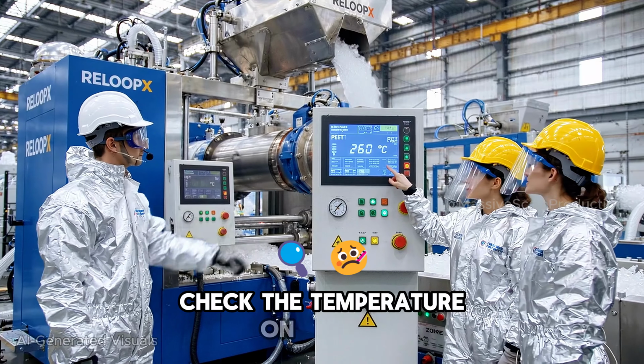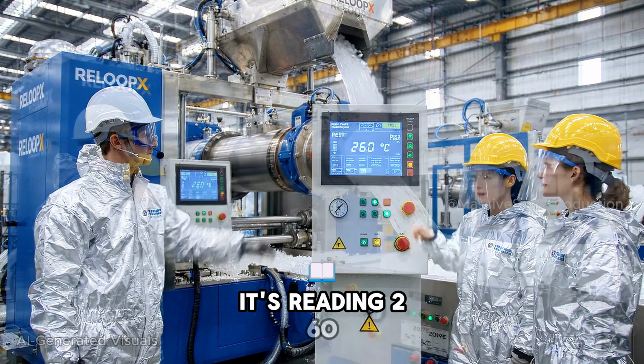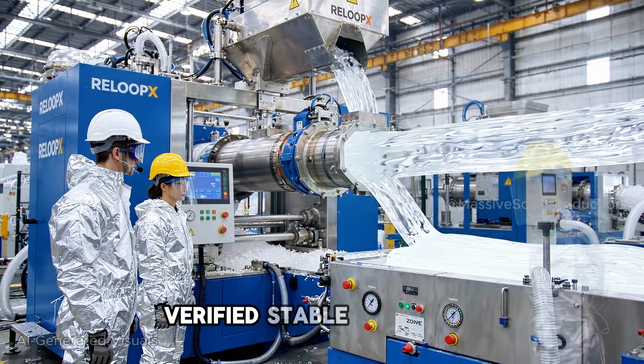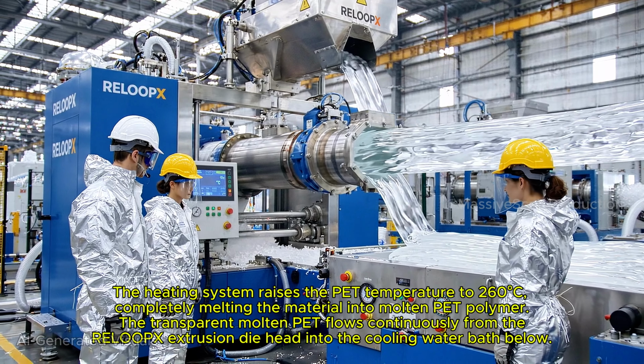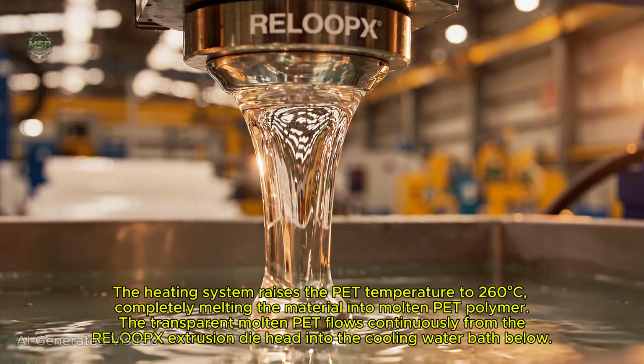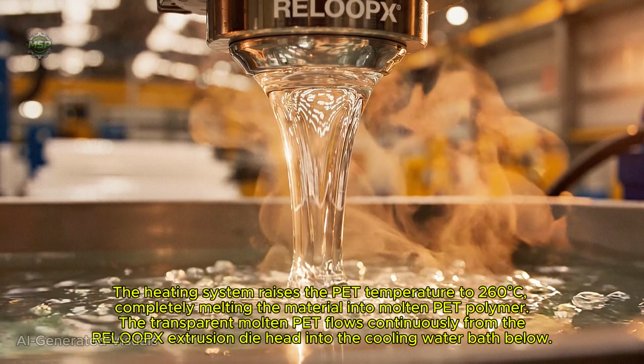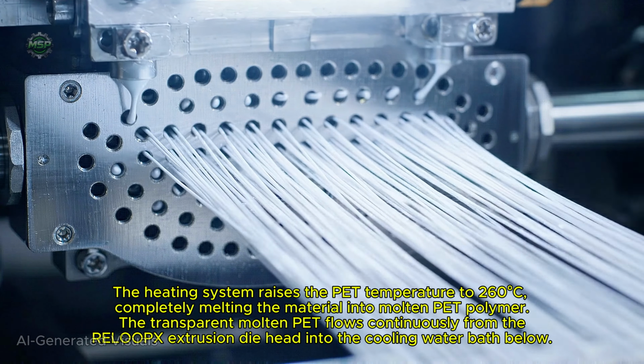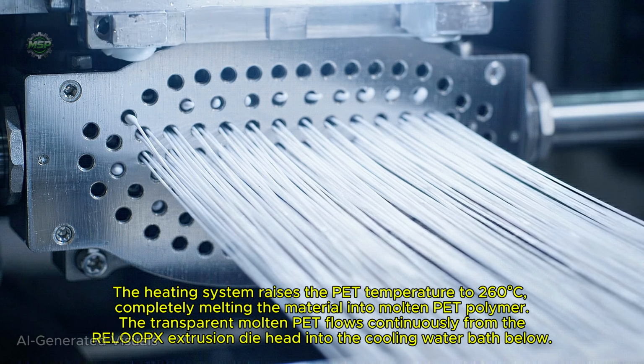Check the temperature on zone 3. It's reading 260. Verified. Stable extrusion. The heating system raises the PET temperature to 260 degrees, completely melting the material into molten PET polymer. The transparent molten PET flows continuously from the RELOOPX extrusion die head into the cooling water bath below.